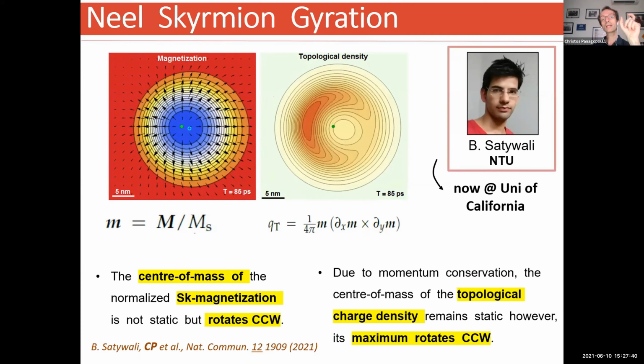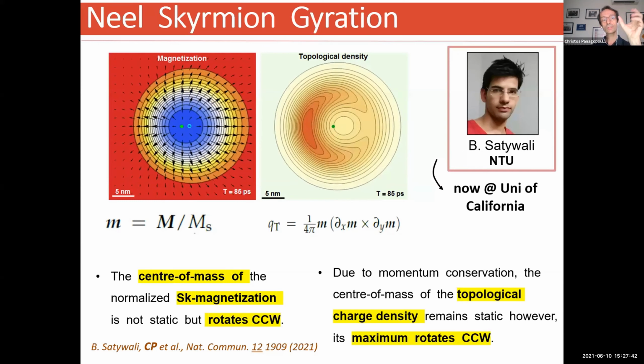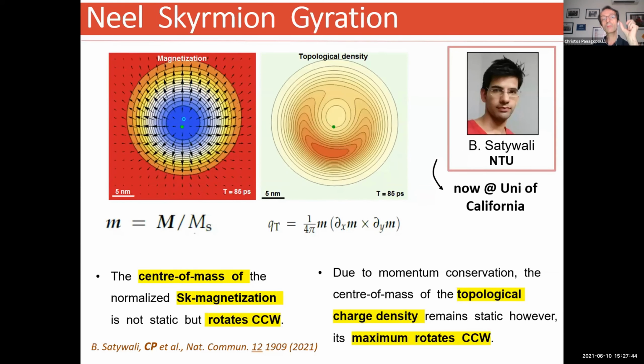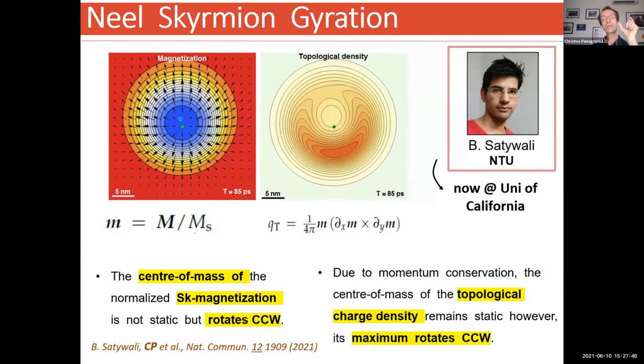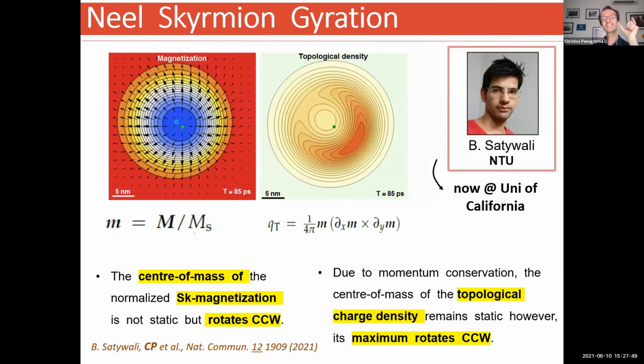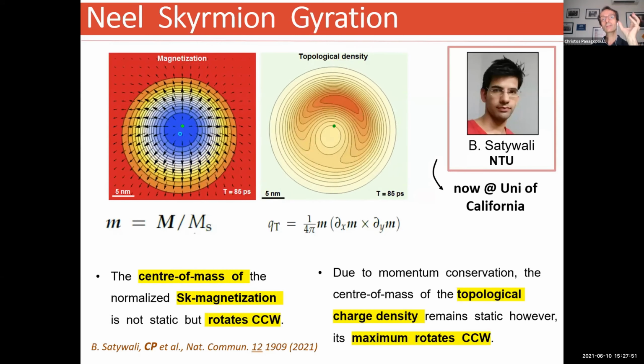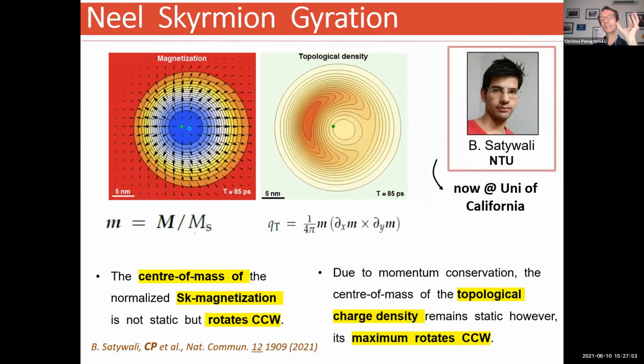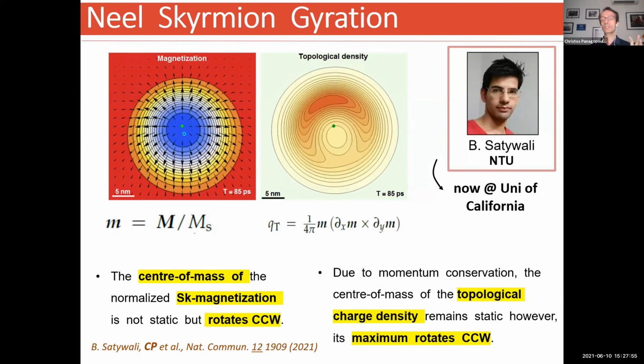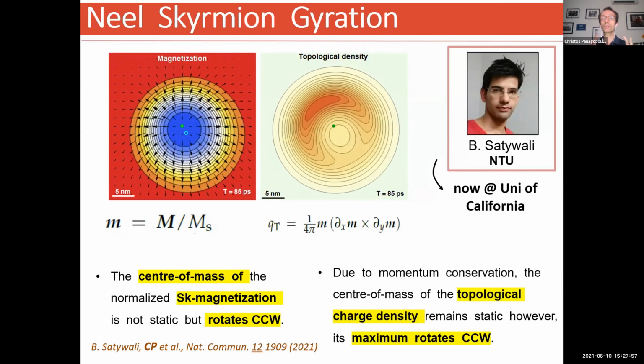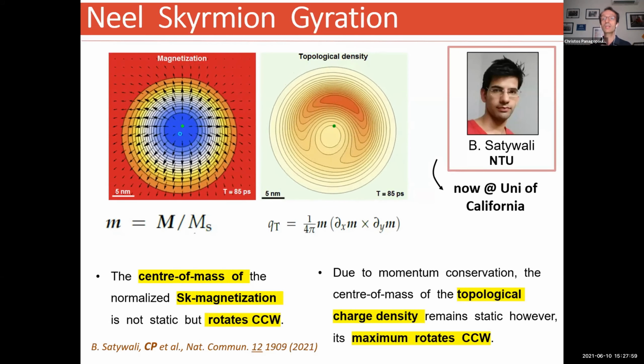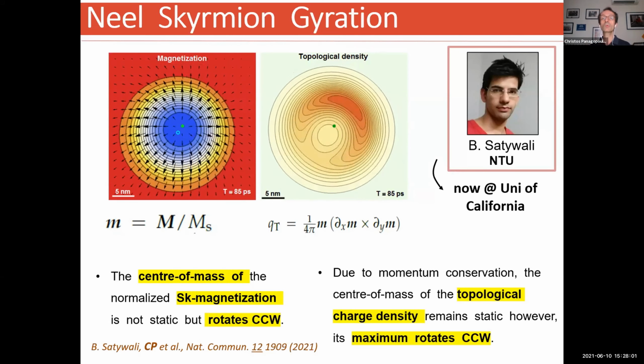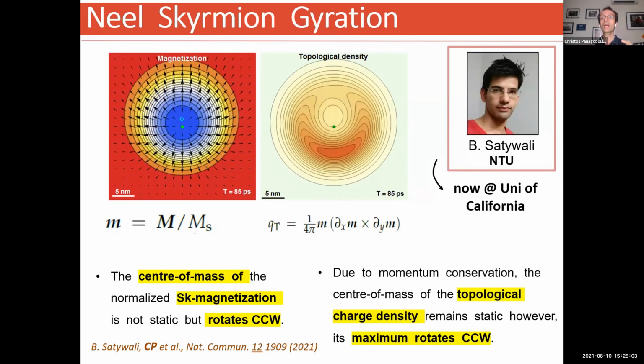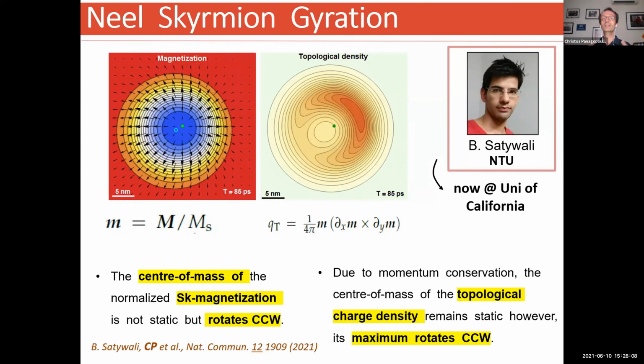So what you see on the left-hand side is the magnetization, and you can see the center of mass of the normalized skyrmion magnetization rotating counterclockwise. And on the right-hand side, you see the topological density, and that is because due to the momentum conservation, the center of mass of the topological charge density of these skyrmions remains static, but its maximum rotates also counterclockwise. So now we know that not only we can create these magnetic textures, but they are rotating counterclockwise and they are Néel skyrmions.